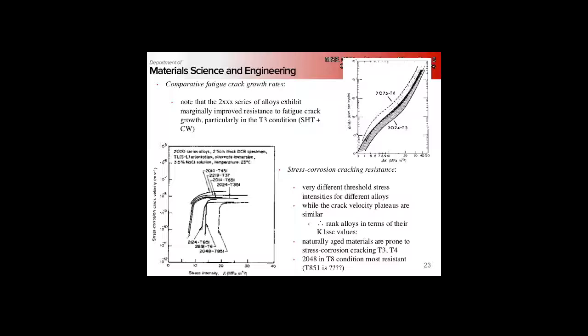Okay, an important application is stress corrosion cracking, which is sort of the linchpin of all of our aluminum alloys. So what this shows here is the crack velocity, and again this is the stress intensity down here. Notice the plateau is about the same.